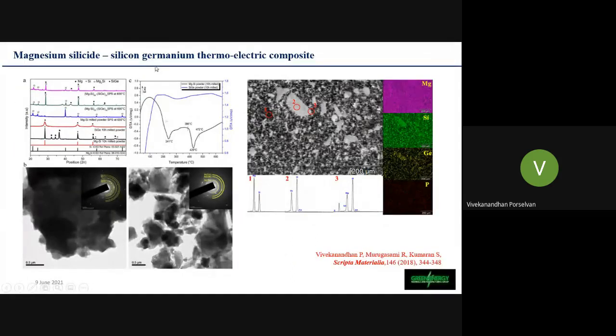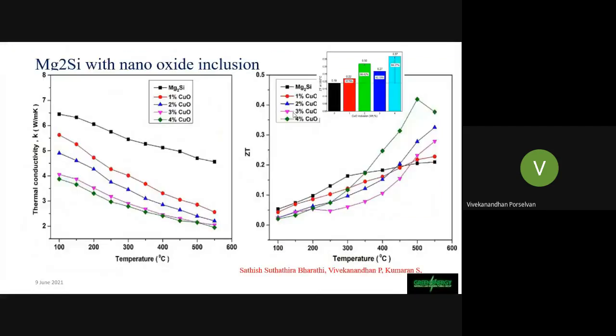And the magnesium silicide silicon germanium composite approach. This is a composite synthesis made of magnesium silicide and silicon germanium alloy. Okay, so from the same image we can see that the magnesium silicide is dispersed in the silicon germanium, and it is creating bigger scattering centers for the phonons.